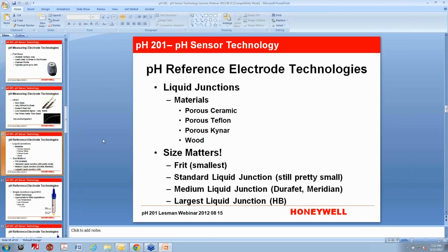That's a poisoning problem. Also, if the holes or the pores are too big, then that allows potassium chloride, depending on its formulation, to get sucked out of the reference area. And if you don't have the potassium chloride, you lose your electrical contact at the reference electrode. And of course, you're just surrounded by air, and so you don't have a stable voltage potential anymore around the reference electrode. So the smallest of the liquid junctions would be a frit,